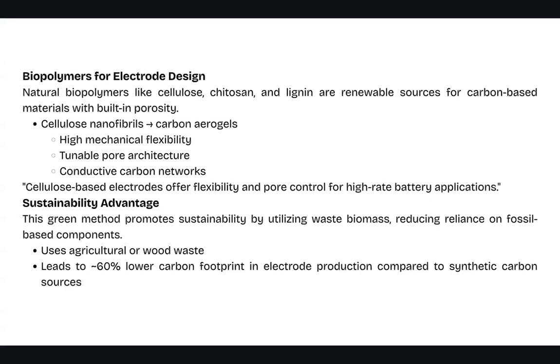So biopolymers for electrode design. What is this? Natural biopolymers like cellulose, chitosan, or lignin are renewable resources for carbon-based materials with built-in porosity. So cellulose nanofibers, which are carbon aerogels, have high mechanical flexibility, tunable pore architecture, and conductive carbon networks. Cellulose-based electrodes offer flexibility, pore control, and suitability for high rate battery applications. One of the main advantages is its sustainability. It's a green method which is going to promote sustainability by utilizing waste biomass, and while utilizing a renewable resource, obviously reduce fossil fuel consumption. It uses agricultural or wood waste, and it leads to around 60% lower carbon footprint in electrode production compared to synthetic carbon sources.